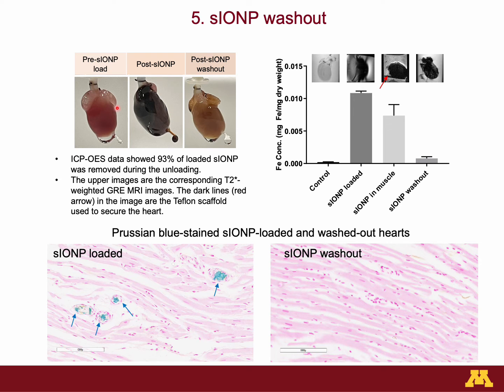And the visual washout efficiency of the type B cannulated hearts was superior to that of type A, as I previously mentioned on the slide. Here you can see the pre-sIONP loaded heart, post-sIONP loaded heart, and post-washout. The efficient washout was characterized by ICP-OES and the residual iron imaged by micro-CT and MRI. ICP-OES data showed 93% of loaded sIONP was removed during the unloading.